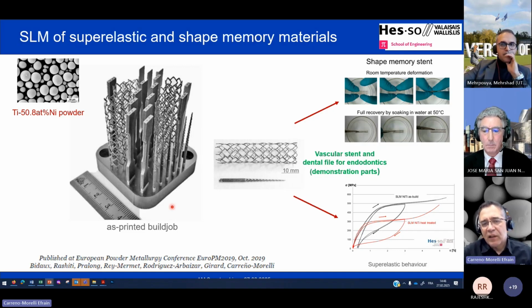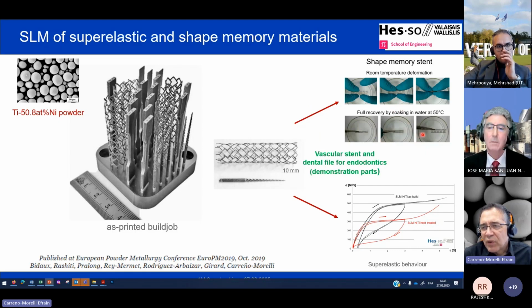And then playing with the printing parameters and with the nickel evaporation, we managed to obtain parts with shape memory behavior and also with superelastic behavior. The shape memory behavior can be seen in these prototypes of stents. Then we managed to change the transformation temperatures to have a recovery of the shape after soaking in water at 50 degrees. For example, it was just the preliminary work, okay?